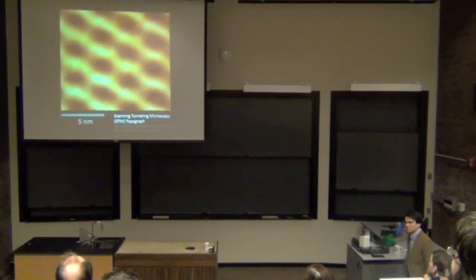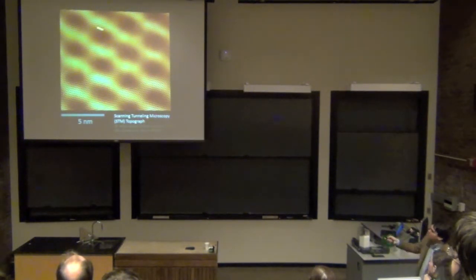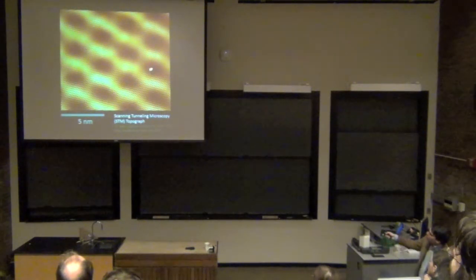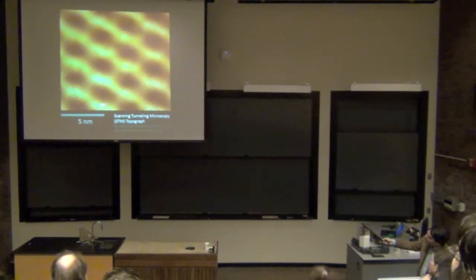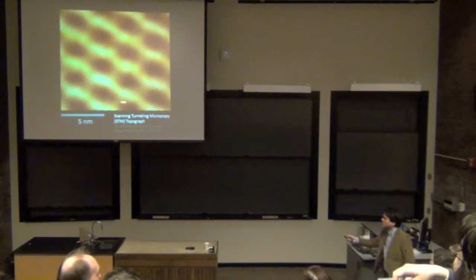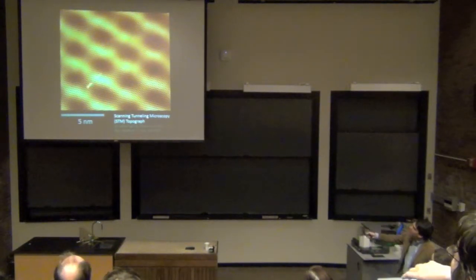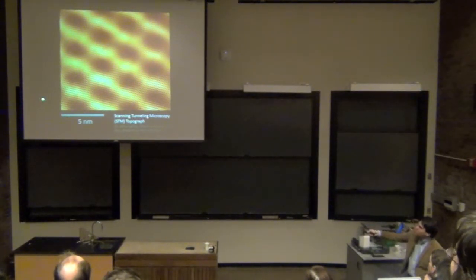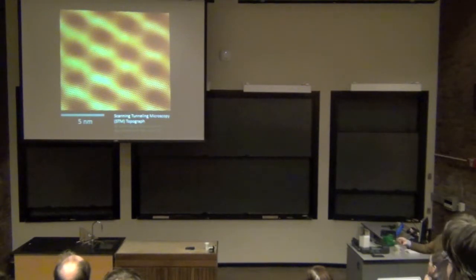So that moiré pattern, that superstructure, is actually seen in scanning tunneling microscopy images. This is an STM image from our collaborators where you can see the superstructure, which is roughly 5 to 10 nanometers long. But underlying that, you can actually see the size of the graphene atoms as well. So we have a very interesting system here with this kind of periodic structure on top.